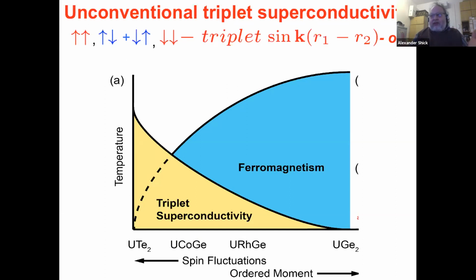In principle, it was a purely theoretical proposal for many years until the first ferromagnetic superconductor was discovered, and it is uranium germanium 2. It was discovered, if I am not mistaken, around the year 2000, so already 20 years ago. And since then there were more developments and more materials came around, like uranium rhodium germanium, uranium cobalt germanium, and finally, about a couple of years ago, uranium tellurium 2 was discovered as an unconventional superconductor. And our American colleagues eventually created some kind of cartoon saying that if you go from uranium germanium 2, which is a ferromagnet and becomes superconducting under 12 kilobar pressure, you go to the left-hand side, you destroy the magnetic ordering, but there are still spin fluctuations which mediate the superconductivity in uranium tellurium 2.